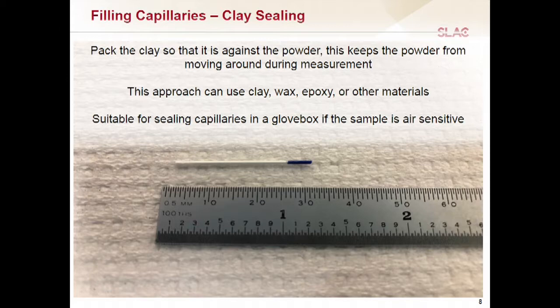And the reason that you want to pack the clay all the way down to be against the powder is that you want to spin the capillary. And if I have loose powder or room for the powder to move inside of the capillary as I spin it, it's probably going to flow around. And what you really want to avoid is that the powder flows in and out of the beam as you're making a measurement, because then your intensities just go up and down in a random way, and that's obviously going to cause some problems.